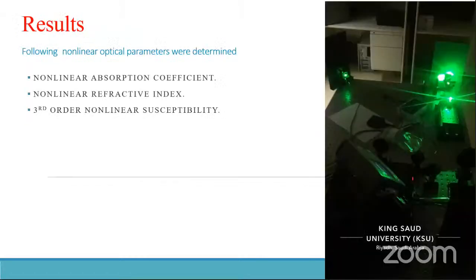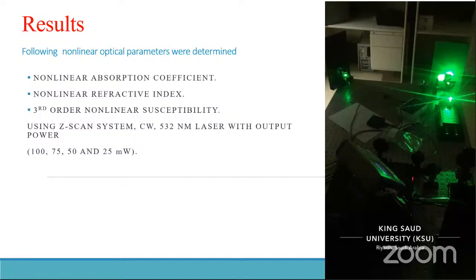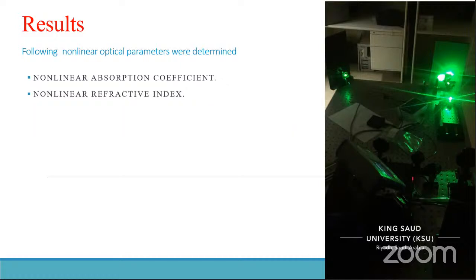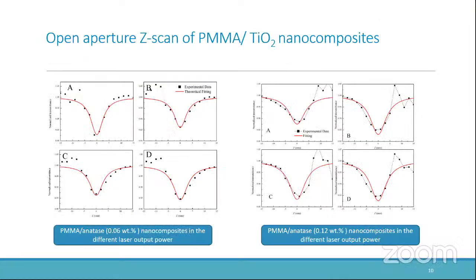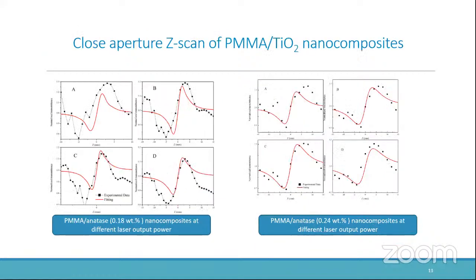So we have measured nonlinear absorption coefficient, nonlinear refractive indices, and third order nonlinear susceptibility using Z-scan profiles with a CW laser of wavelength 532 nanometer. So here are the profiles of open aperture Z-scan. These are taken at different laser output powers and are used in the calculation of nonlinear absorption coefficients.